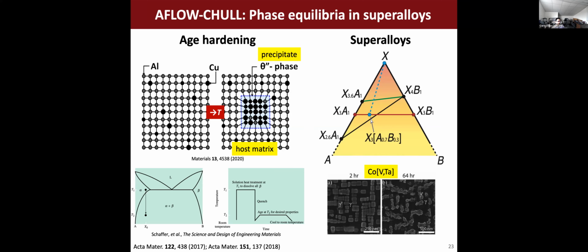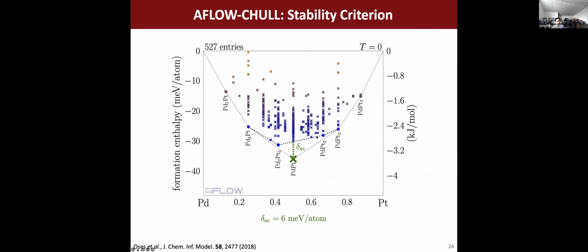No problem. All right, so let's keep going. That's one way of using the data that we have, one example of how we use this data from the convex hull. So this is another one. We've created a descriptor that's called the stability criterion. I talked about the distance from the hull from the perspective of the top. If I have a system that's going to decompose, there's going to be a particular distance down to the bottom of the convex hull, and that driving force is that distance.